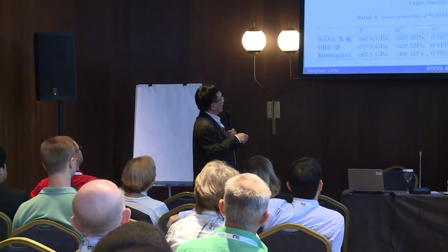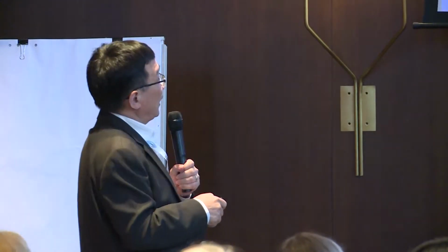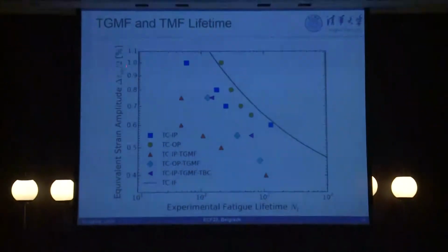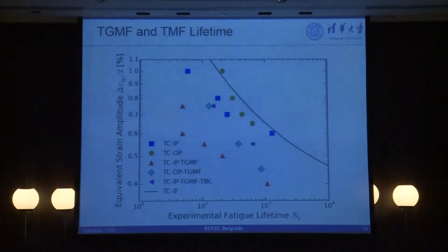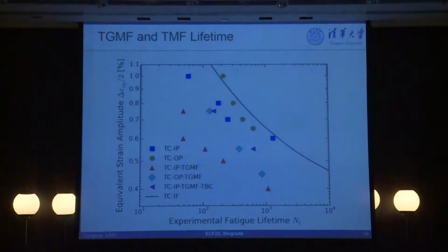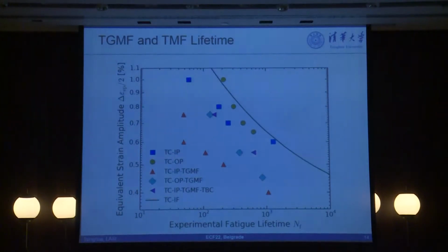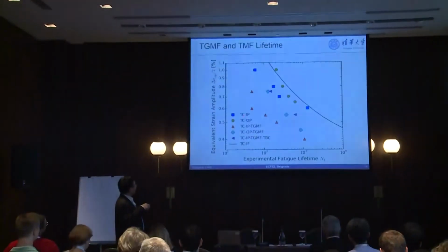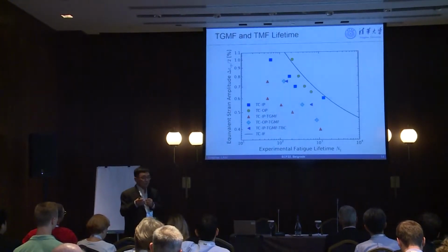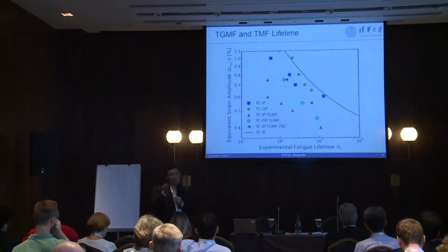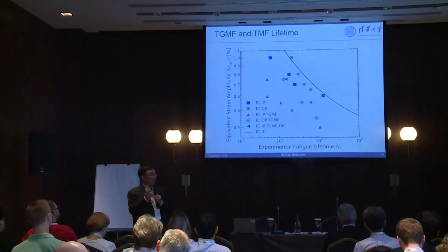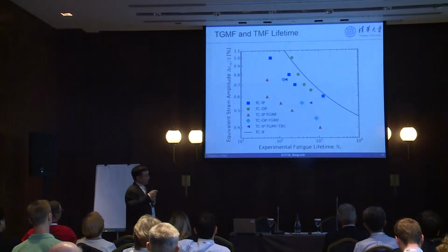And I would say the differences between materials are not so sensitive in this case. For a significantly larger deviation, we see the effect of loading. You see here the strain control case, a mechanical strain control test. What you see here is the equivalent mechanical strain, and on the horizontal axis you see the life of it. We performed, as I said, different phase angle cases. Therefore, you see in phase and out of phase. Out of phase means you see the maximum temperature, but in that case you have minimal mechanical load. They are exactly 180 degrees shifted.